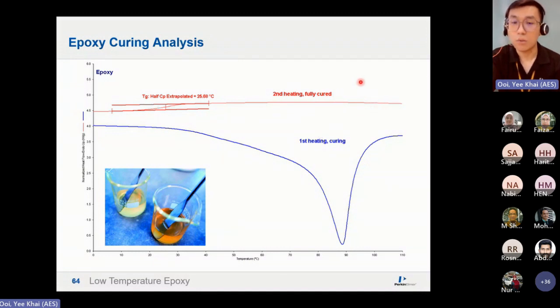So this is a thermoset material, not a thermoplastic. If it's a thermoplastic, it is crystallization, because crystallization is also exothermic. Regardless of how many times you cool, you are going to see the crystallization peaks. Okay, but not for curing material. Curing material only once. Once it's fully cured, it becomes a flat line at the same temperature, as you can see. So this is not a reproducible transition. Okay.